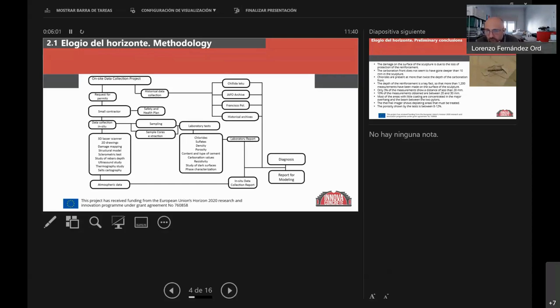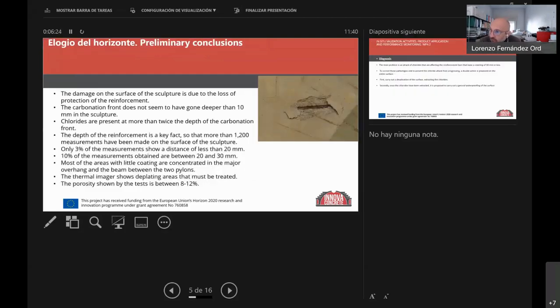And that was really useful for us. So we finally took samples from the sculpture. We did a lot of analysis on the surface, and with that, finally we came to a diagnosis of what was happening to the sculpture. The sculpture had this kind of detachments that you see on the right. That's a rebar, a steel bar in the concrete, which corrodes, and when it corrodes it expands, and when it expands it breaks the concrete.